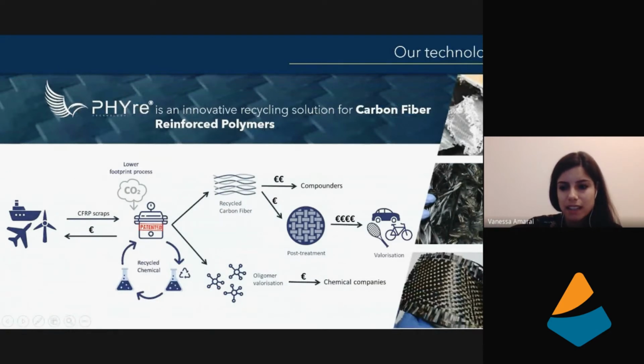Actually, today the main recycling process for this kind of material is pyrolysis, as Professor James just presented. However, pyrolysis does still have a quite high carbon footprint, especially because of the high temperatures that they use, and they can damage the fibers a little bit as well. So we have limited capacity of using this carbon fiber, especially in high value materials afterwards. So the PHYre process was born in order to have a very high quality material without damaging the carbon fibers, that can be used in high value applications.